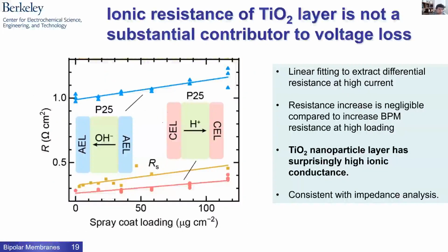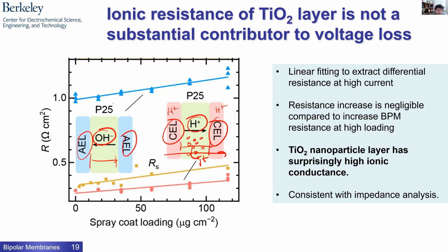So we went in and said, okay, we better measure how well hydroxides and protons can move through these TiO2 catalytic layers. Remember, they're just TiO2 particles, no ligands, native surface functionalization, flooded with water. Now, instead of making a bipolar membrane, we just take two membranes of the same polarity. So this is a proton conductor, a proton conductor. They're both selective conductors for protons. So if we drive current through there, we are forcing the TiO2 layer to move protons. Okay, so we just change that thickness and measure the differential resistance. We do the same thing when you have hydroxide conducting contacts to our catalyst.